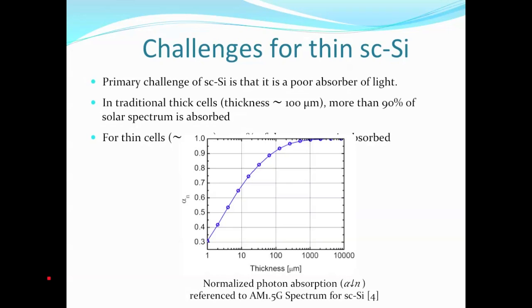So what are some challenges for using thin silicon wafers for photovoltaics? So the primary challenge is that silicon is a poor absorber of light at very thin wafers. So we have here a plot of the fraction of the AM 1.5 G spectrum absorbed in a particular thickness of silicon. So we can see for traditionally thick wafers that more than 90%, so at 100 here, more than 90% of the AM 1.5 G spectrum can be absorbed in that 100 microns thickness of silicon.